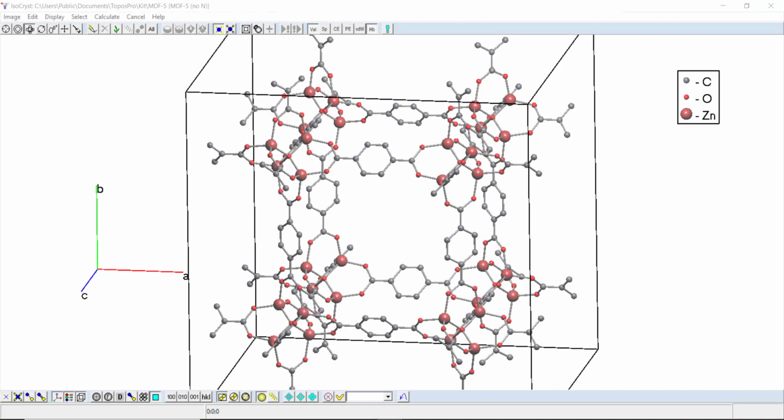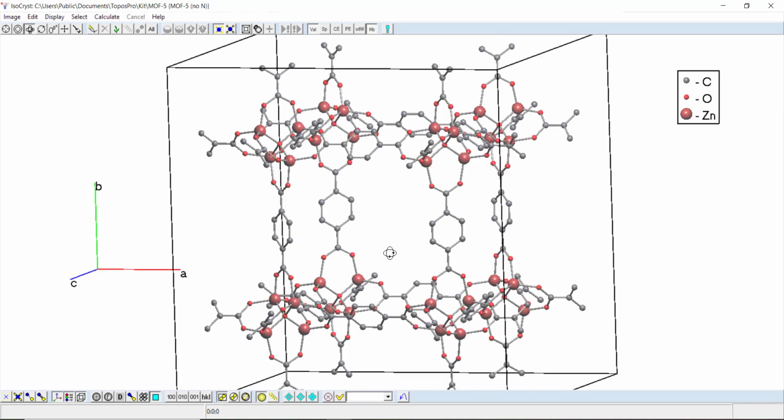We found through previous research that you also need to account for the species that fill the pore in the MOF when you're growing the crystal structure. So that's one of your key units of growth, the species that fill your pore. We had adsorbed nitrogen to begin with, but we're just going to simplify that down into a single dummy representative atom at the center of each pore. So we know we need to add a species right at the center of the system here. That'll be our 0.5, 0.5, 0.5 coordinate.